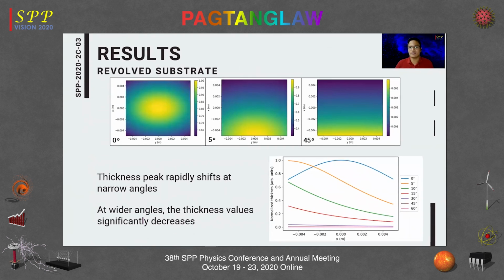Now, these are the results. So these color maps illustrate how the thickness profile rapidly changes as the angle increases. As you can see, the peak rapidly shifts at narrow angles. So this is at 5 degrees. The center of the thickness profile is already near the edge of the substrate.